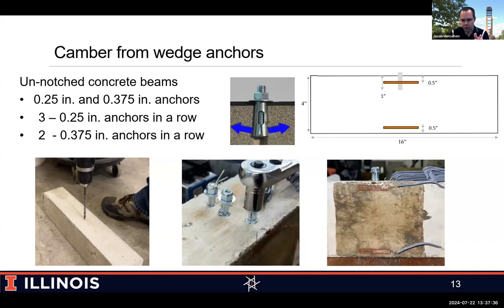With the smaller anchors, we could pretty easily get them in a line of about 3 across the surface. Again, remember, this is a 4-inch wide member, so getting 3 in there is probably, we really started to see problems if we tried to get a 4th one in there. So we limited it to 3 with the 1/4-inch anchors and 2 with the 3/8-inch anchors.